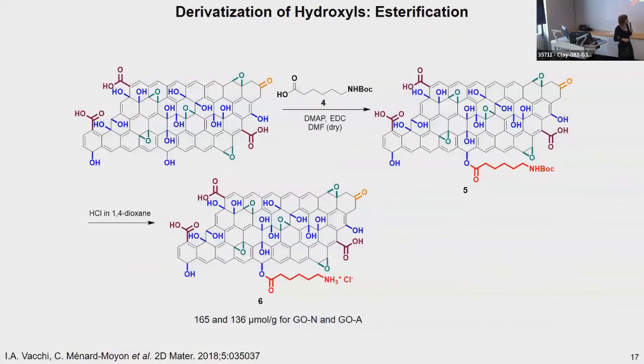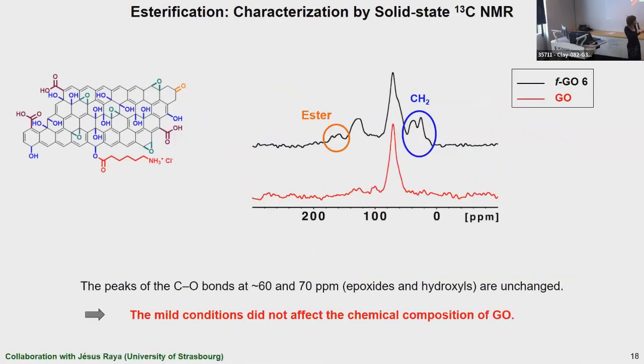The second reaction that we explored is the esterification reaction, taking place between the hydroxyls on graphene oxide and this carboxylic acid derivative linked to a terminal amine protected with the Boc group, allowing to form this ester bond. So this reaction was performed in the presence of coupling agents to activate the carboxylic acid here. And the last step was the cleavage of the Boc group to have the ammonium moieties, allowing to assess the level of functionalization. So to confirm the occurrence of the reaction, we used solid state NMR.